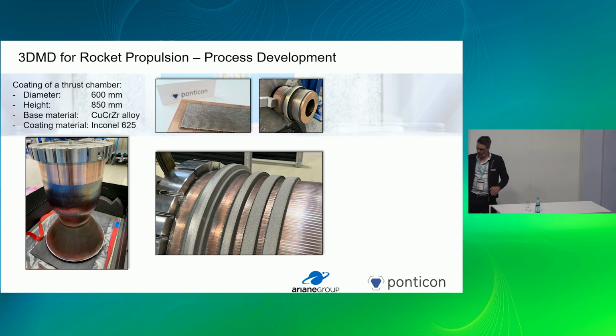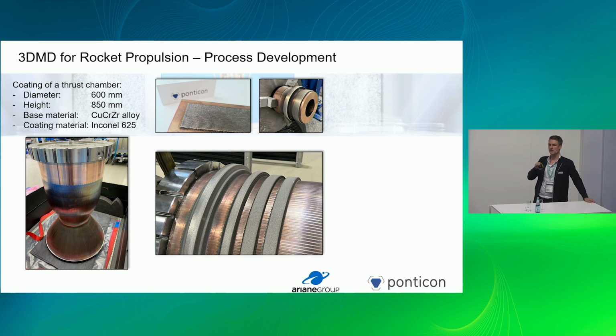Because what happens if you apply an Inconel jacket on top of this copper chrome zirconium layer, things would start pulling inward. So it was quite difficult to get it off the tool because there was a lot of stress and also forces pulling towards the inside. And that's actually what we wanted to find out in this first step of process development when applying those larger rings. And at the same time also understanding how the temperature develops in the part, because what you want to avoid at all costs is a change of properties of the part that you are working with. So it was really key to make sure that we do not exceed a certain temperature in the thrust chamber. We have to keep in mind we're shining 3 kilowatts of laser power onto this part continuously for many hours. So obviously it warms up, and this is something we have to keep an eye on.